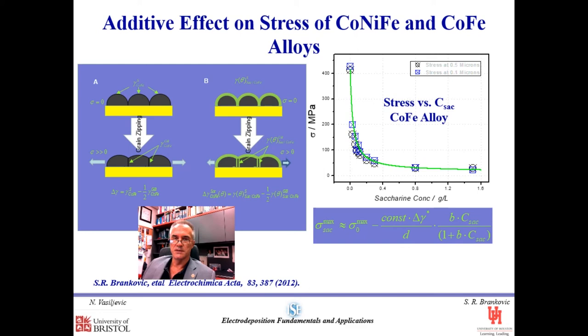One of the models that I'm going to discuss basically assumes that additives change the thermodynamics of the surface and change the surface energy of the growing metal and also the grain boundary energy of the growing metal. What that really means is that, because of the different energetics, the benefit of grain zipping to reduce the overall energy of the system is not so large anymore, because the surface energy that's supposed to be decreased by the grain zipping process is not so high anymore. So the driving force for grain zipping decreases, and that overall results in a decrease of the stress in the deposit.